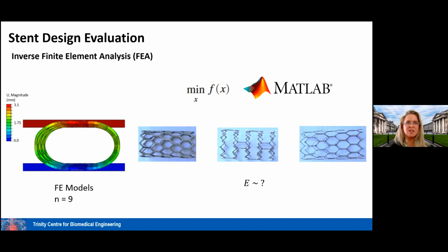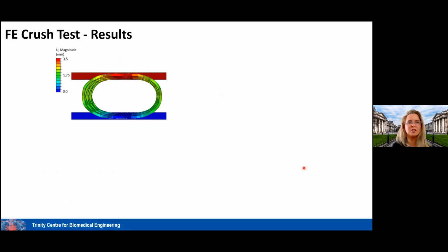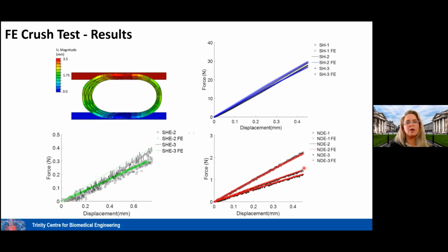So we crush these in the same ways we have done experimentally, and we determine what Young's modulus we have to put into the stent here in order to replicate what we see experimentally. And that essentially tells us then that that must be the Young's modulus, or the stiffness of the titanium in its print state. So we did that for all those different stents, those 9 different stents, so 3 from each of these geometries. And we were able to get out results that we could match our Young's modulus.